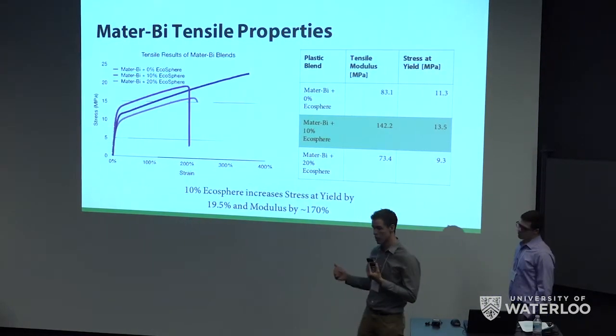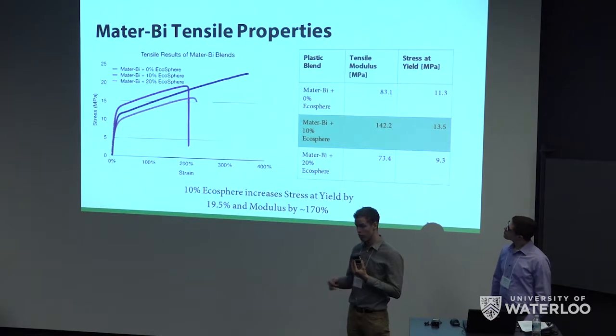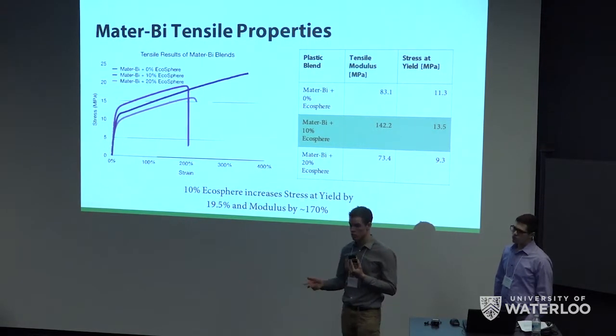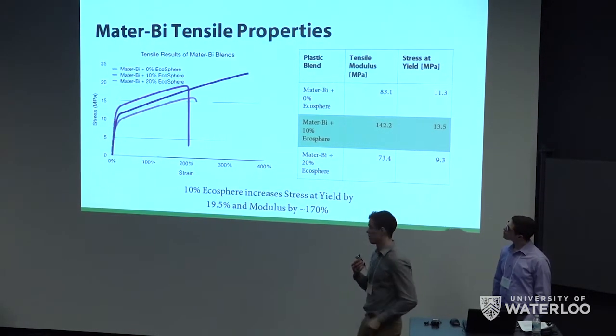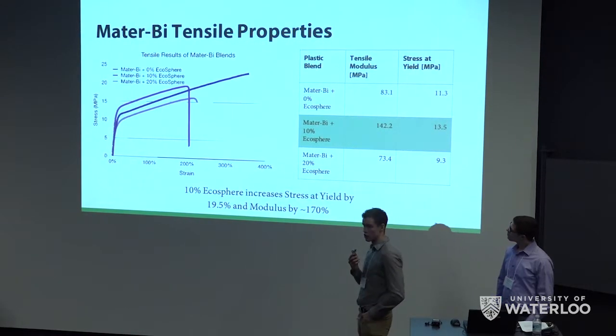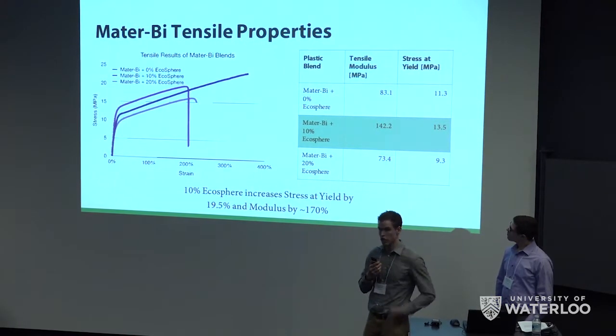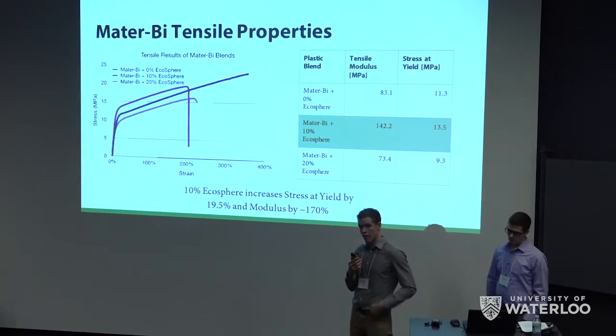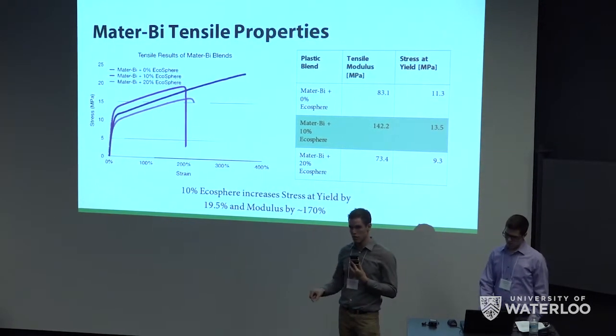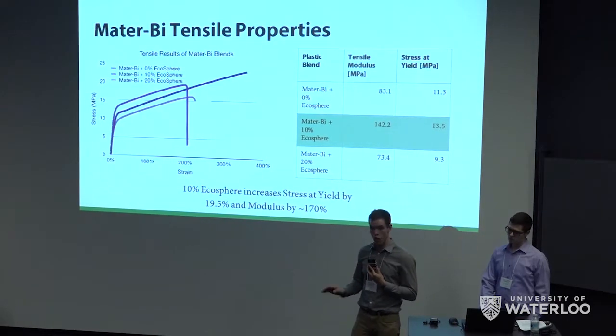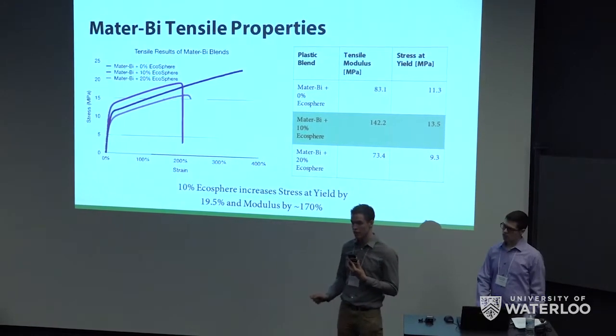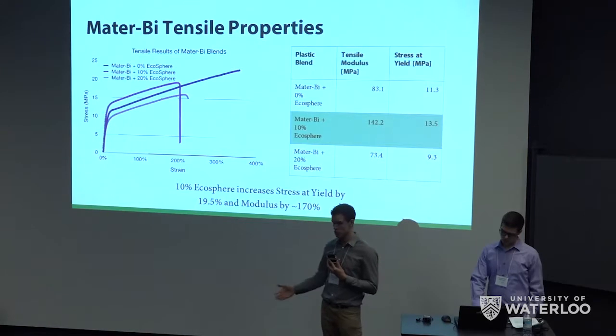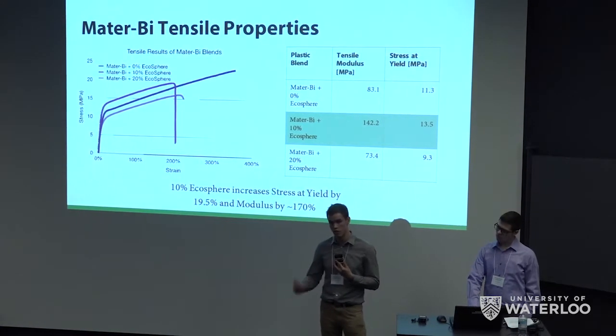Fortunately, when we mixed Mater-Bi, which is a thermoplastic starch, with our nanoparticle, which is a starch-based molecule, we got a much better result. We ended up with a 20% increase in the stress at break, or stress at yield, and a 170% increase in the tensile modulus. This translates to a bag that, if it's the same thickness, is 20% stronger, or if you have a 20% thinner bag, you have the same strength. So this can directly be translated into savings on material cost.